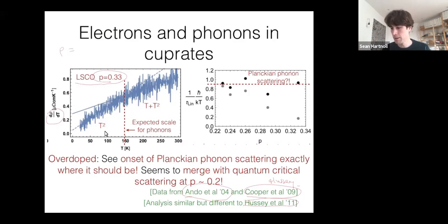If the resistivity is a constant plus T squared, then the derivative is B plus CT. Okay. So here at low temperatures, the fact that it's linear with intercept pretty close to 0 is telling you that at low temperature, this thing is 0, and this thing is not. So the resistivity is going like T squared with no T-linear component, right? And this T squared is what you might expect for some strongly correlated Fermi liquid, all right?